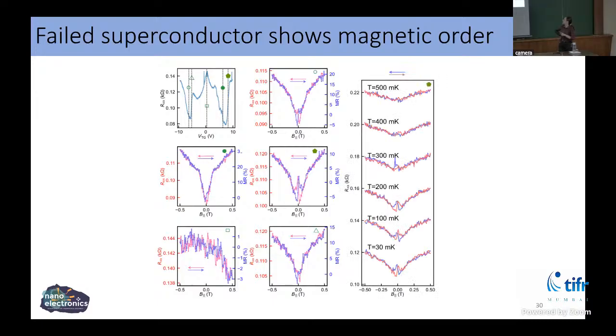Even in this device the hysteresis dies out with temperature, but it happens at a much lower temperature. Earlier, it was dying out close to 900 millikelvin, and here, even at 500 millikelvin, the hysteresis is gone. So our understanding is that this magnetic order is present over a larger range of twist angles in the system, but the superconductivity is more special and is more confined to a rigid range of twist angles.